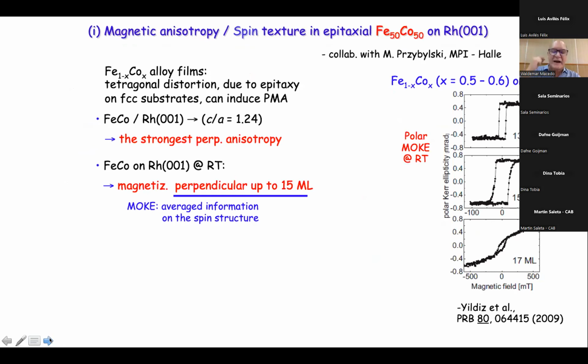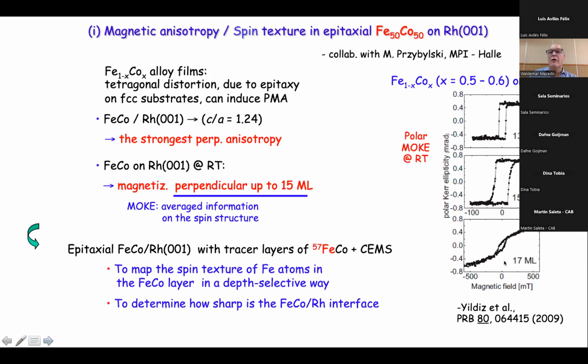Perpendicular magnetic anisotropy is very important for different applications, for memory, for devices. And the tetragonal distortions play a very important role in the induction of perpendicular magnetic anisotropy. And iron cobalt on rhodium is a model system. And people have shown, by doing MOKE measurements, that for this system, doing polar MOKE, you can get, let's say, square loops until 15 monolayers.